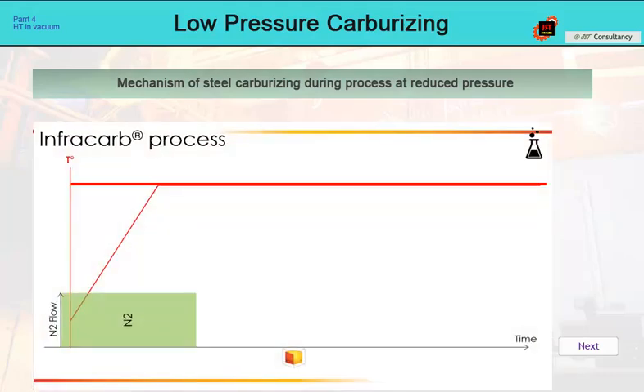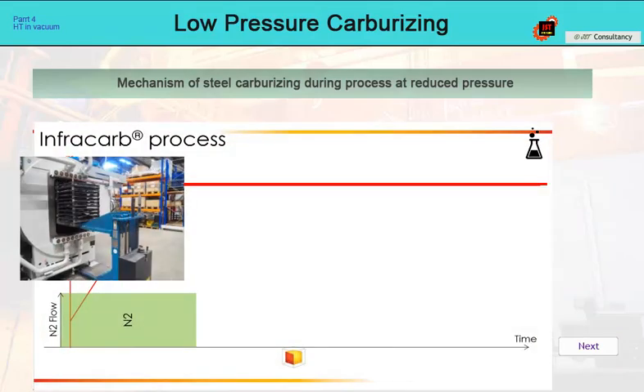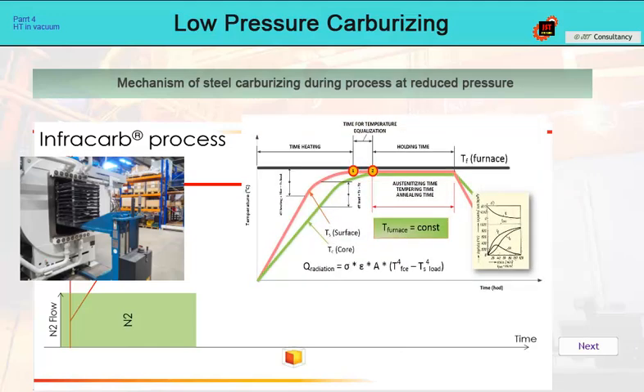The process begins with the batch being loaded into a heating chamber, which is usually permanently at working temperature. The working procedure is therefore similar to that of multi-purpose furnaces. Because the batch is cold, it must be heated to the desired temperature throughout its full profile. This heating usually takes place in nitrogen, with convection heating up to 850 degrees Celsius, above this temperature in a vacuum. To fully heat the batch, a sufficiently long period must be applied to stabilize the temperature.